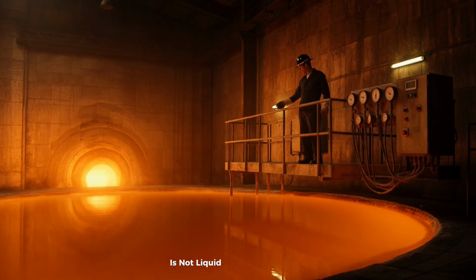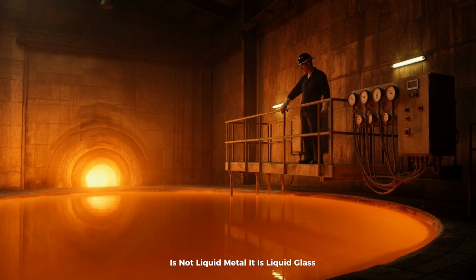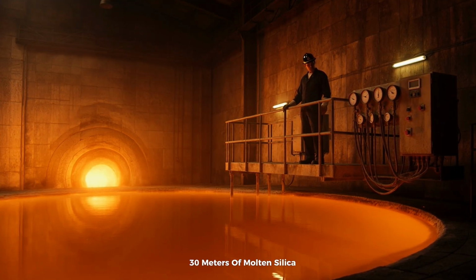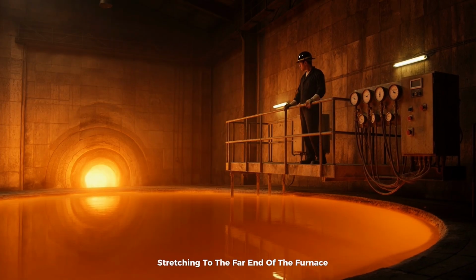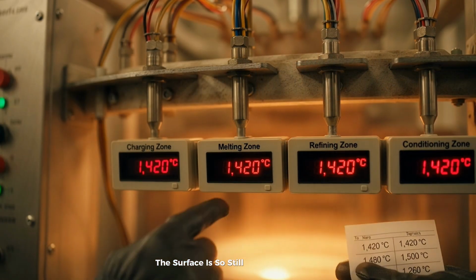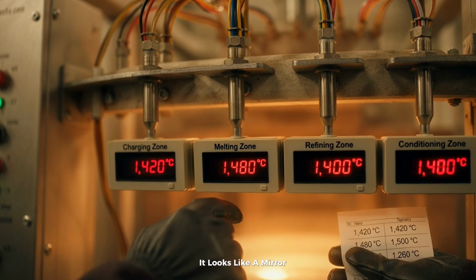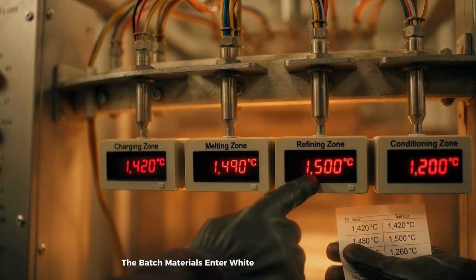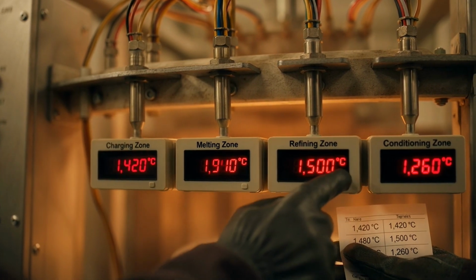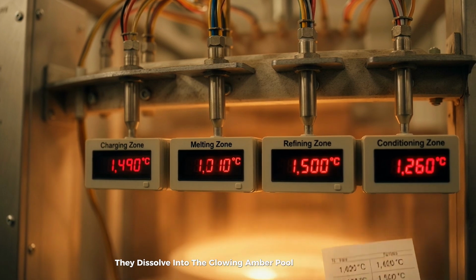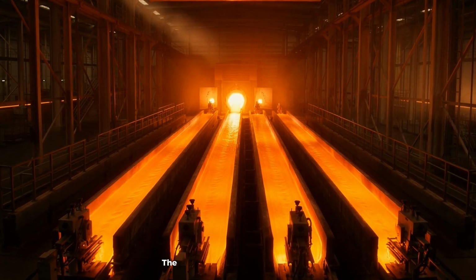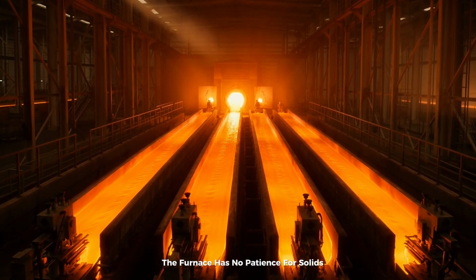That amber lake you are looking at through the viewport is not liquid metal. It is liquid glass, 30 meters of molten silica stretching to the far end of the furnace. The surface is so still at this temperature it looks like a mirror. The batch materials enter white and cold on the left side. They dissolve into the glowing amber pool within 15 minutes. The furnace has no patience for solids.